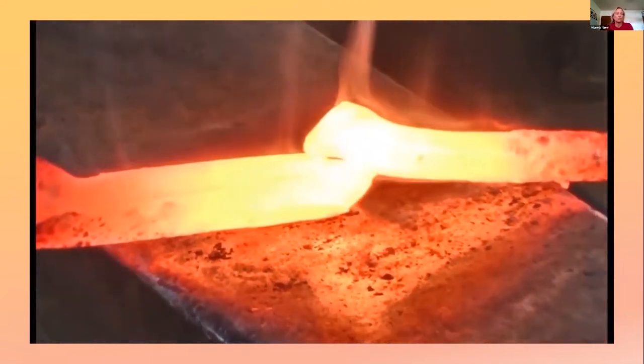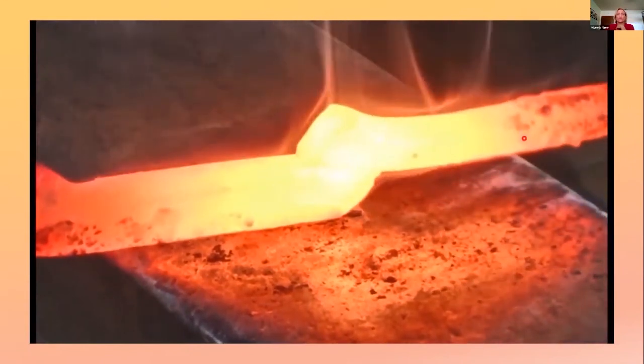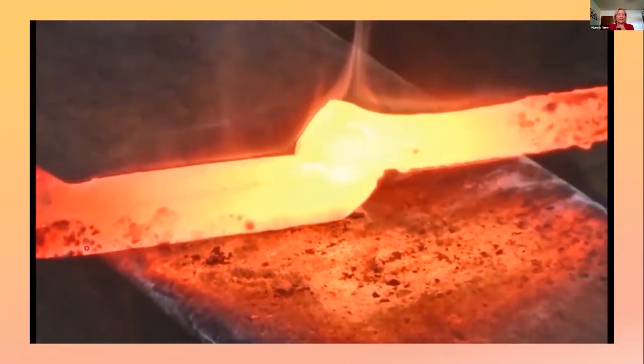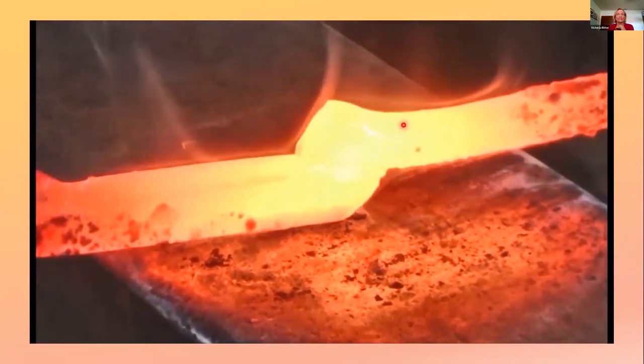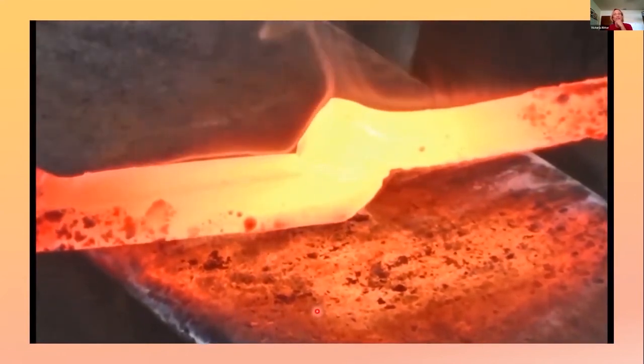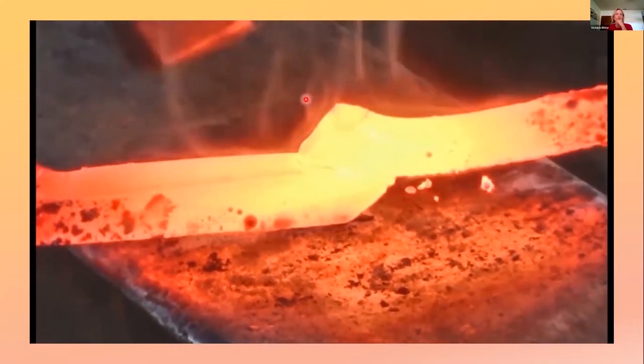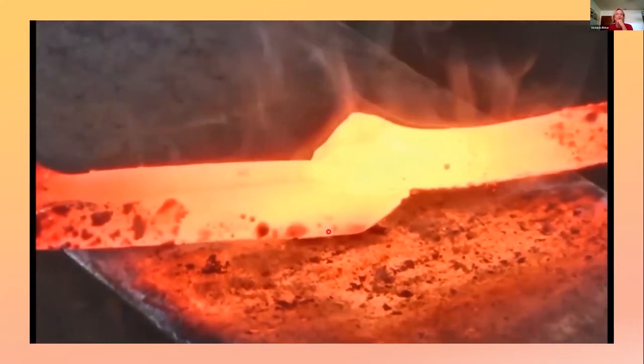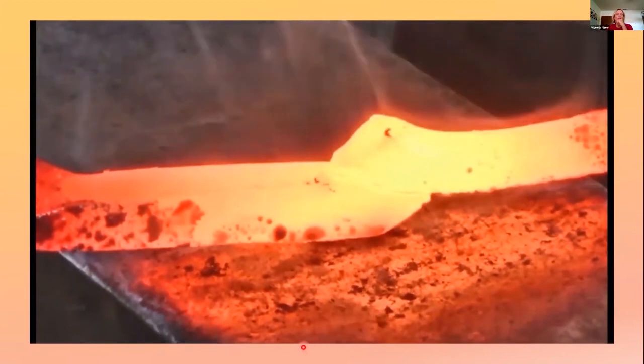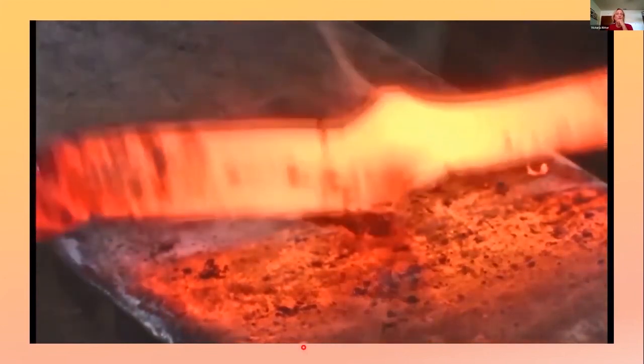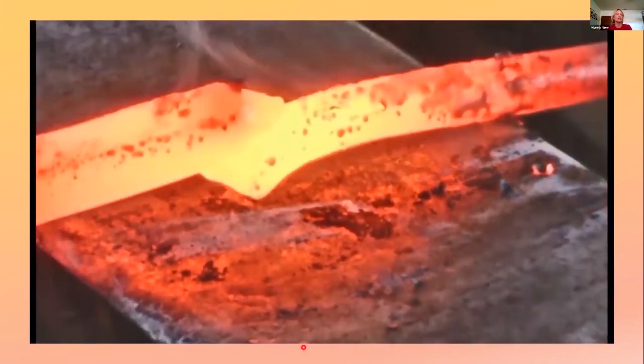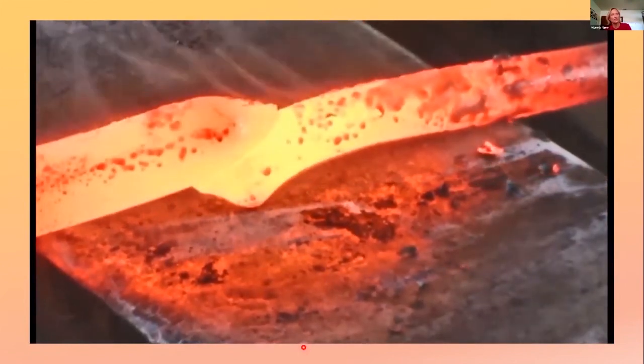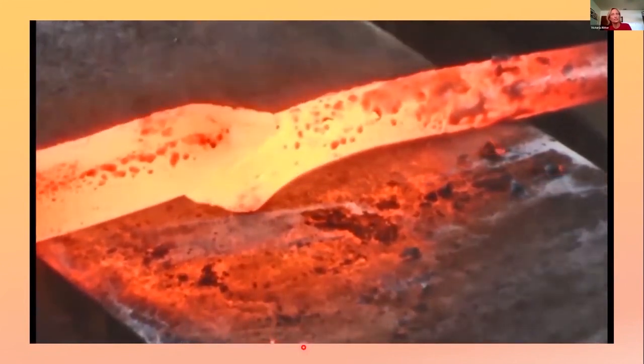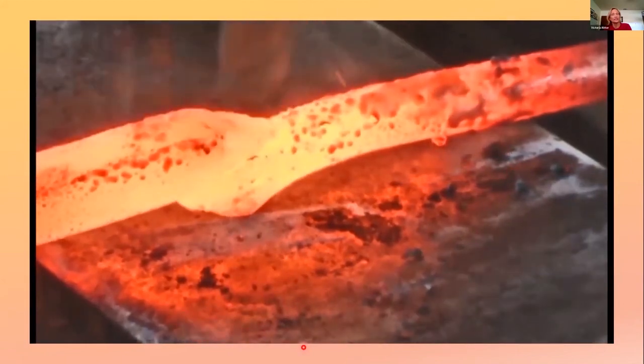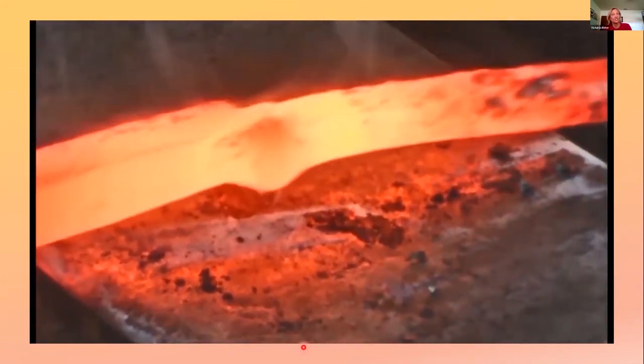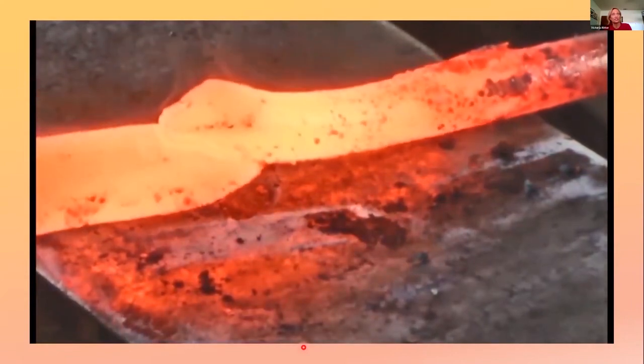A nice slow-mo view of forge welding. Notice how the pieces were rested on the sides till you had this in exactly the right spot. Hit once on top, follow that down to blend in that toe. Turn it over, same thing, hit it on top, blend in the toe, and you're forge welding at this point, not forging. So the pieces are hardly deformed.